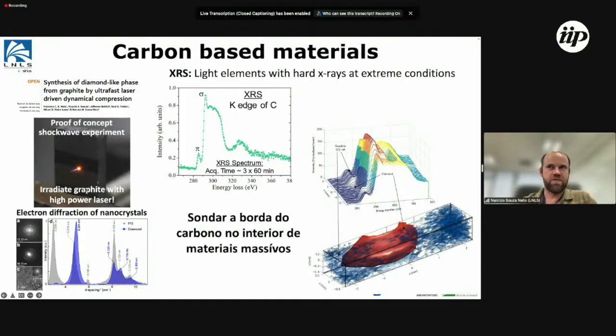We also diamondized graphite here using lasers, and that is one kind of thing that we can probe with this spectroscopic technique, where we can look at the pi or sigma bonds of carbon with hard X-rays. There are even people who showed that we can look at this in 3D. So we have this 3D information of the spectroscopy data at each voxel, not a pixel, but a 3D pixel, so it's a voxel, and can look at these electronic bonds as well.